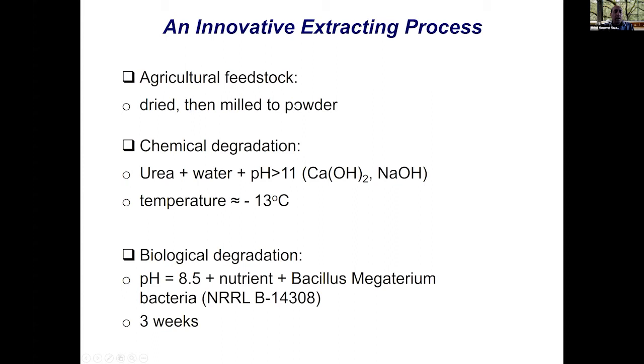We get agricultural waste, we dry it and mill it to powder. In some cases, we have just used the dry material, but our experience showed that milling can improve the performance of the process. Then we do a chemical degradation process using urea and an alkaline solution at low temperatures. After that, at room temperature, we do biological degradation. We adjust the pH to around 8.5, and using a safe bacteria for 3 weeks, we do the biochemical degradation process.